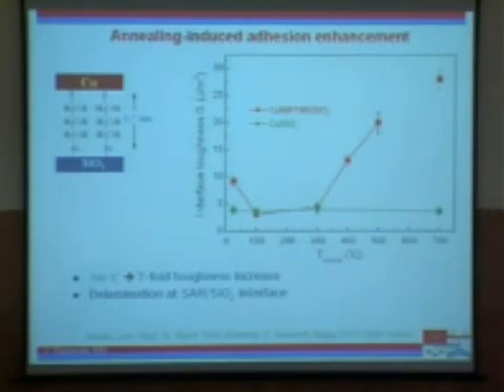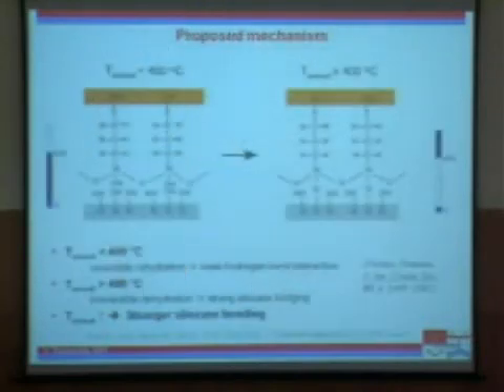I mean, this is totally counterintuitive, because these molecules are organic molecules, and normally people study these on surfaces, and these desorb, and above 300 they're not even considered for any use. But this suggests that we can use these at high enough temperatures if we can use them at interfaces as opposed to surfaces. And let me just tell you what's happening, and I'll just show you the modeling calculation and spare you the experimental part.